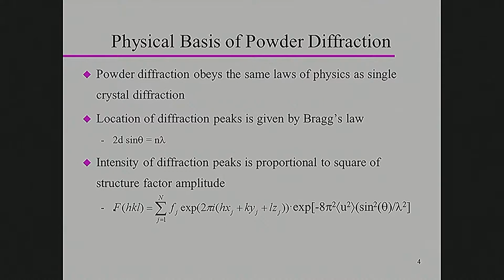Now, let's talk a little more about powder diffraction. The first thing to point out is that the physical basis of powder diffraction is exactly the same as what you've heard so far in Christine's talk for single crystal diffraction and in all the lectures up to this point. We still work with Bragg's law. It gives us the location of the peaks, and the intensity of the diffraction peaks is still proportional to the square of the structure factor amplitude.